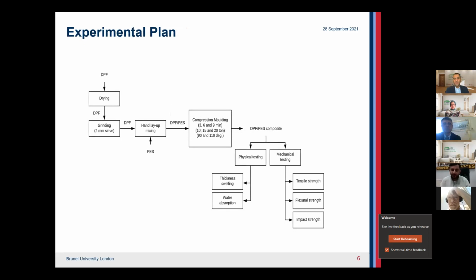So the experimental plan that I was investigating is the compression molding for 3 different durations, which is 3, 6, and 9 minutes, and 3 different pressures applied, which is 10, 15, and 20 tons, at 2 different temperature degrees, which is 90 and 120. Unfortunately, the parameters that I have used are based on a collection of different researchers that have done the same methodologies on different natural fibers. And I have taken the region of the minimal and the maximum and tried to allow a bit of increment increase to show if there is any difference in developing the composite or any effects on the physical and the mechanical properties.